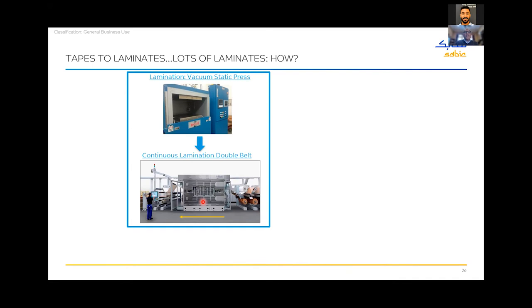And here we invested in our lab capabilities and the center of excellence, what we call a double belt press. A double belt press is one in which, if you follow my cursor, we can bring in several rolls of tapes. We can bring in different colors of tapes. You can bring mixed materials here. It really depends what you're trying to do. And you can bring in all of these materials here on the left-hand side and pass it through, collate it, collect all the materials together and pass it through this continuous double belt process here, where both heat and pressure are applied as the material is moving transitory across right to left. And then on the right-hand side, you actually get your laminate at the end of the day in one shot.